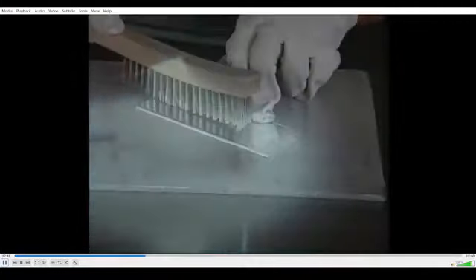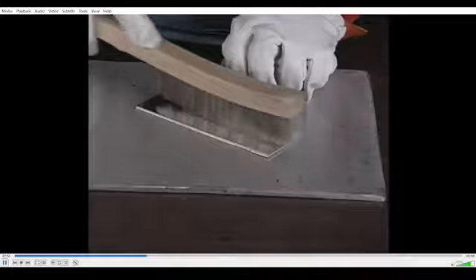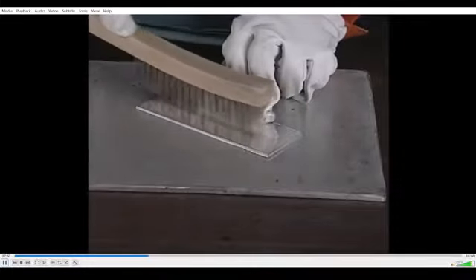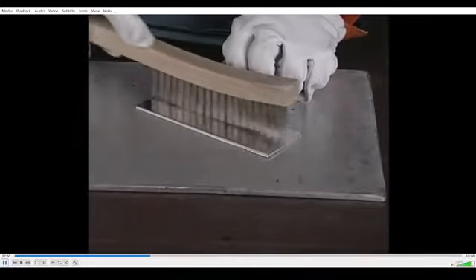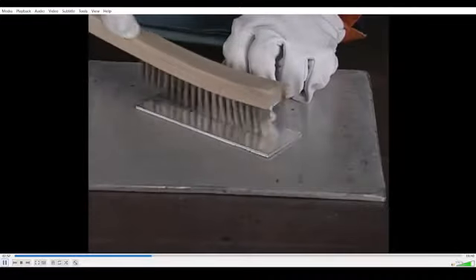The arc shows that during the positive portion of the AC cycle, while current is flowing in the direction of the electrode, ions bombard the surface of the negatively charged aluminum. The sparks are actually tiny pieces of aluminum oxide as it's blasted away by the ions. This is called cathodic bombardment or cleaning action. Brushing with a stainless steel wire brush immediately before welding is always a good idea when you're working with aluminum because it helps break up the oxide coating.